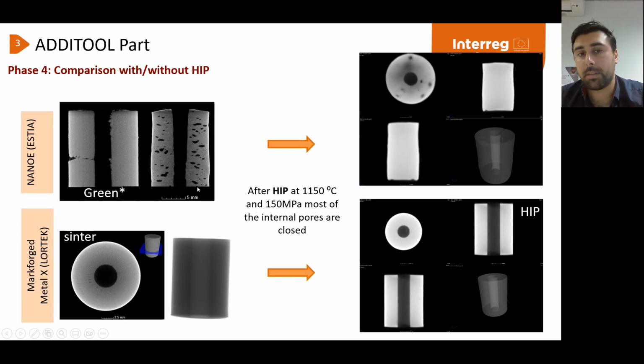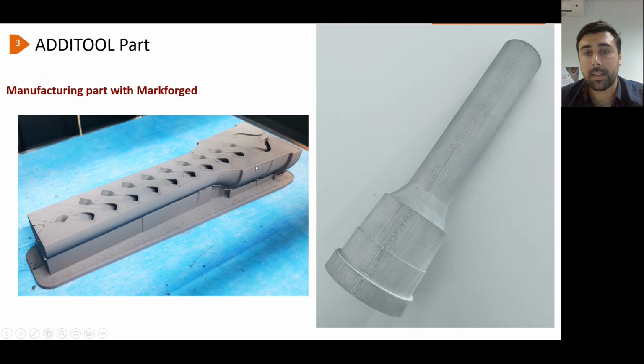This is only a little specimen, but the part we have to manufacture, like this part for SOMOCAP, is about 200 millimeters in length. This was manufactured by LORTEK with Markforged Metal X. Even though the part is cylindrical, it was not made vertically. The manufacturing was only horizontal, okay? Because during the debinding and the sintering process, the dimensions of the oven are not enough to place this kind of part vertically.